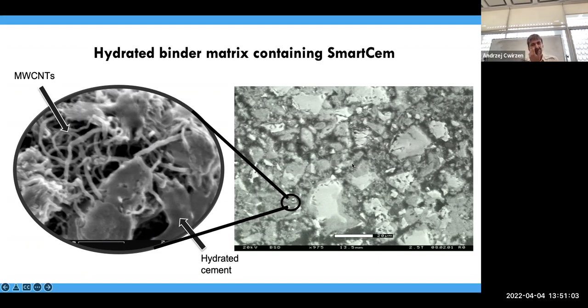In contrast to the solution where you use the water suspension, where those carbon nanofibers agglomerate, this one ensures that you have really uniform dispersion everywhere. In the other solution, you could have some agglomerates here. So instead of improving your mechanical and electrical properties, you would actually worsen both of them.